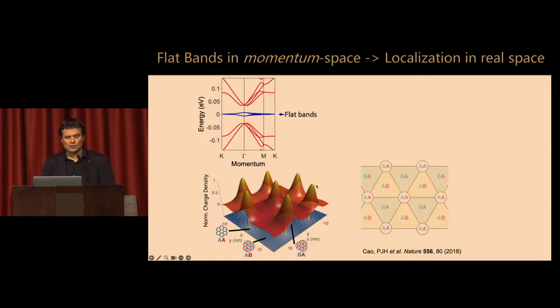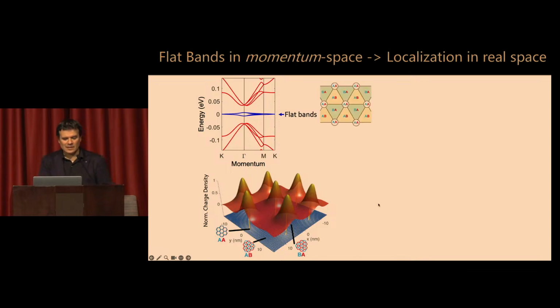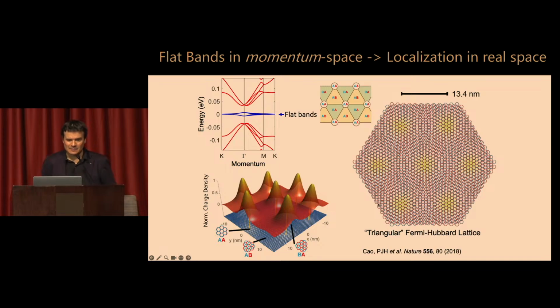Okay? So from the top, magic angle graphene looks like this. It looks like these regions of so-called AA stacking, where locally the carbon atoms are on top of each other. But because of the small twist angle, the atoms get out of registry, and in these regions of AB and BA stacking, the electrons do not like to be there. In a slightly more realistic schematic, this is what magic angle twisted bilayer graphene looks like.